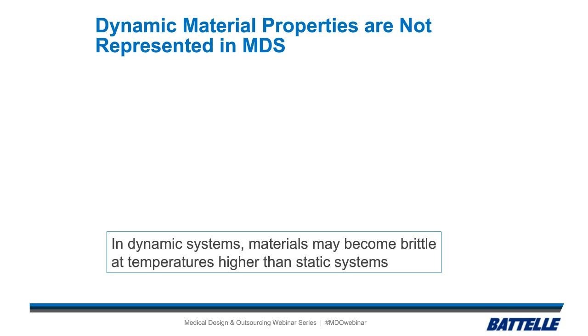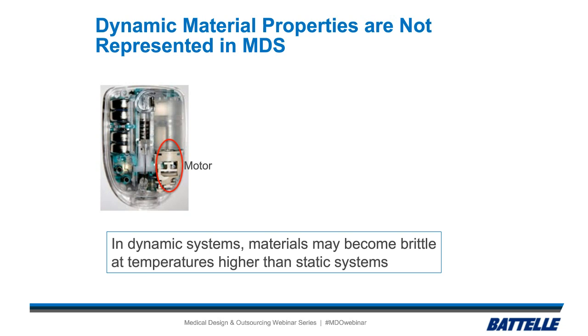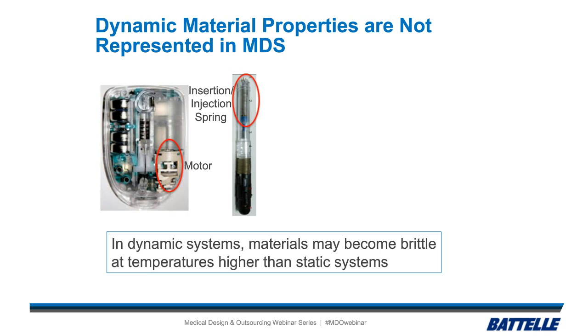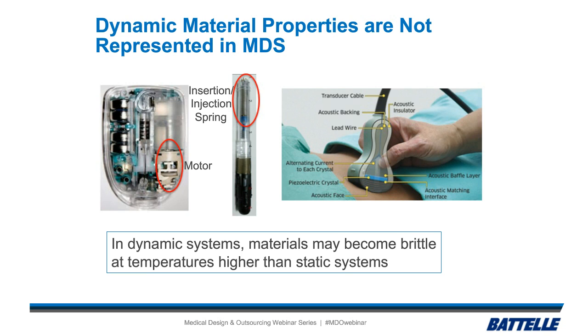So materials may become brittle at temperatures higher than static systems. So if you think about maybe a drug delivery device that has a motor in it, so you get a little bit of oscillation when that motor's running, those materials may become brittle at a higher temperature than you expect. Same thing with a spring-driven device where you have an insertion or injection spring, and there's a very high-frequency event that happens quickly upon the actuation of that device. Those materials, again, could act brittle when you don't think they should at room temperature. And finally, something like this one with the piezoelectric crystal in it, that's going to have some vibration. And amplitude matters as well, so you have to take that into account. You can test for this dynamic dependence using a dynamic mechanical analyzer. So a DMA is a great piece of equipment to use to see how much your material properties shift due to a frequency change.